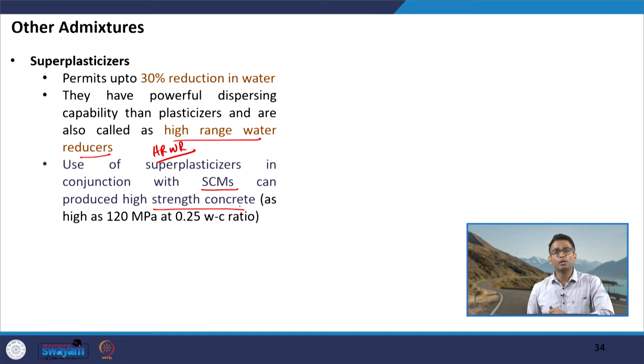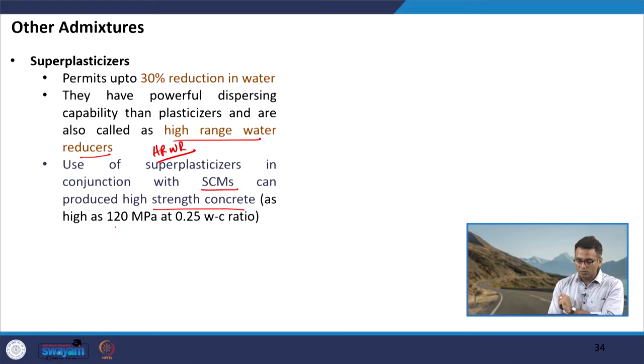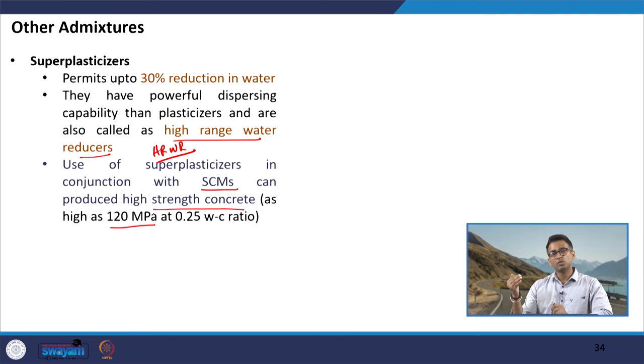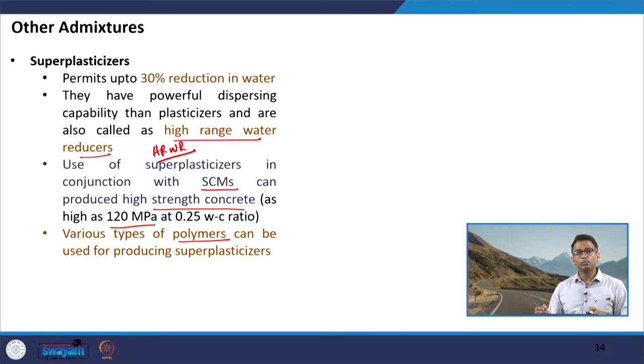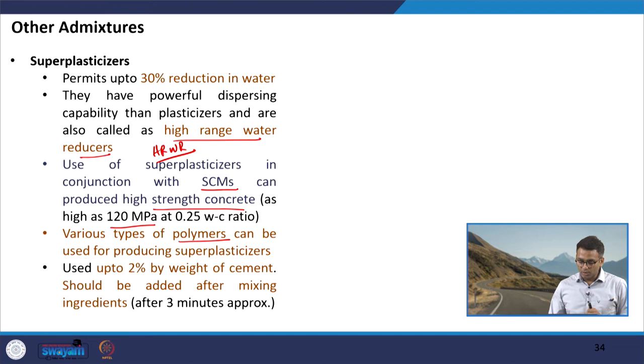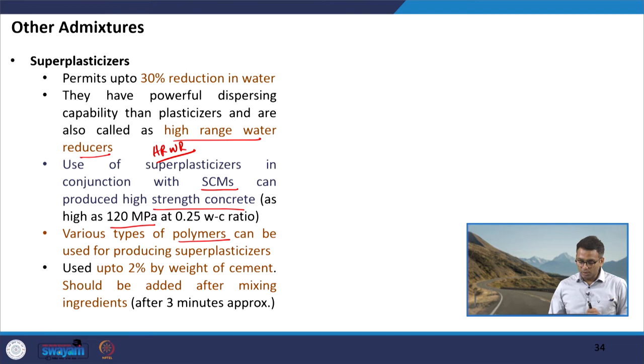Even at a water-cement ratio of 0.25 — a very low ratio — without superplasticizer, the mix would be very dry and difficult to work with. By adding superplasticizer, we can maintain workability similar to conventional concrete at w/c 0.35 or 0.4, while achieving very high strength due to the reduced water-cement ratio. Polycarboxylate ether (PCE) is one of the products popularly used as a superplasticizer.